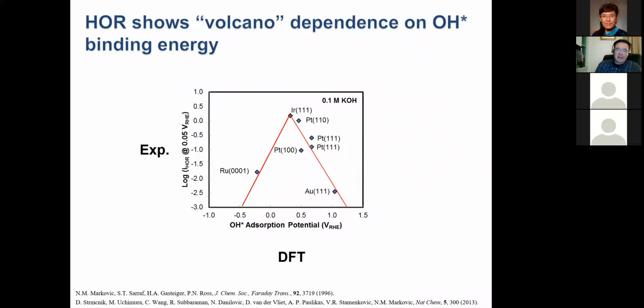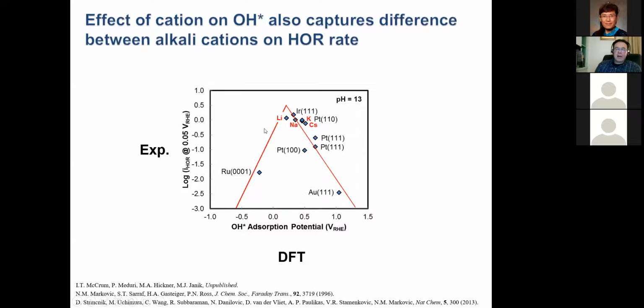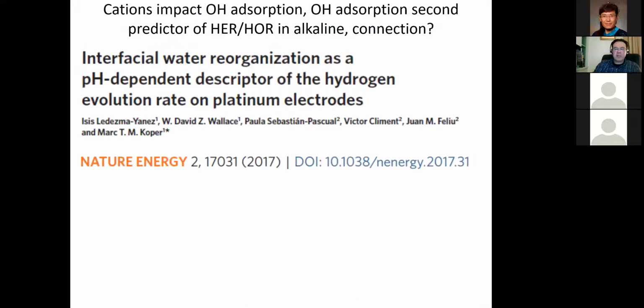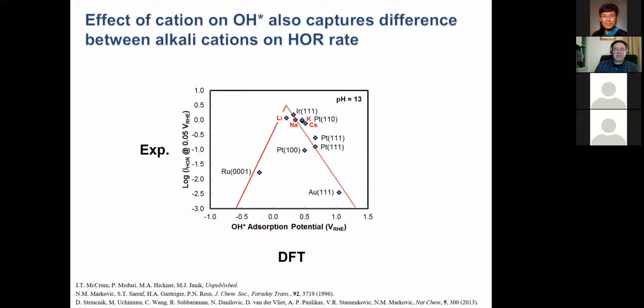Now, if we start adding other single crystals of platinum, it seems to be filling in, with some noise, and I'm still only on one side here, but it's not too bad. If I then also just change the electrolyte from lithium, sodium, potassium, and cesium hydroxide on a polycrystalline platinum, it still looks like it's forming a bit of a volcano. So it's hard to have perfect proof there, but there does seem to be some indication that hydroxide adsorption potential is predicting the hydrogen oxidation rate